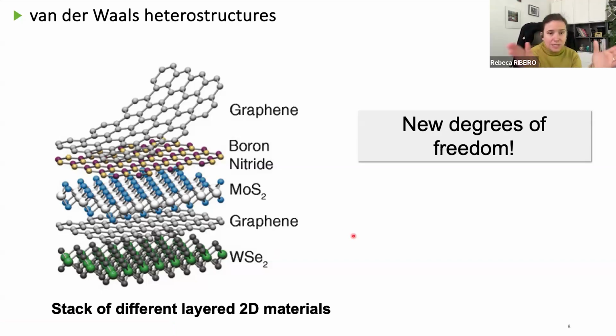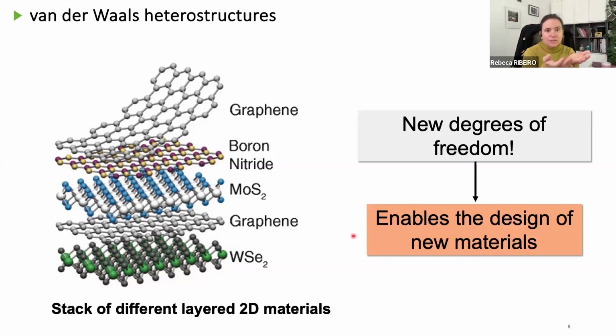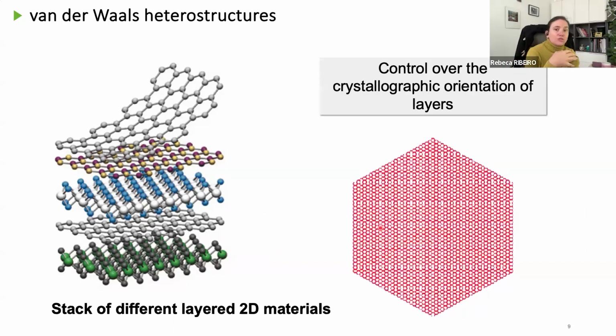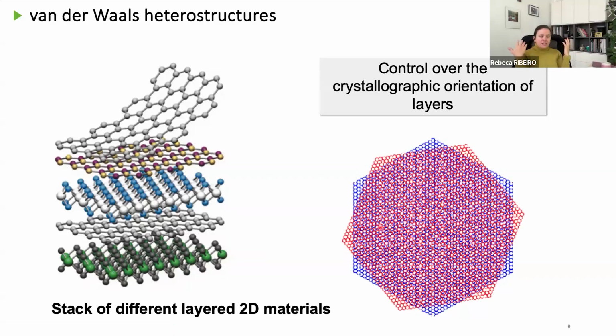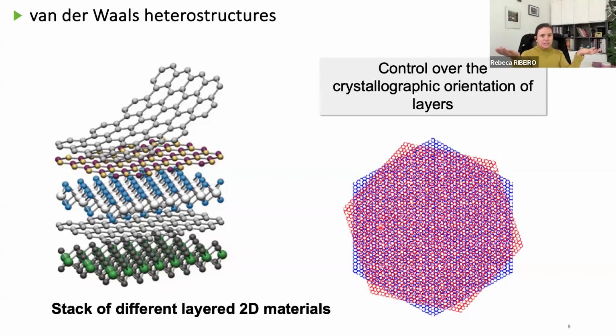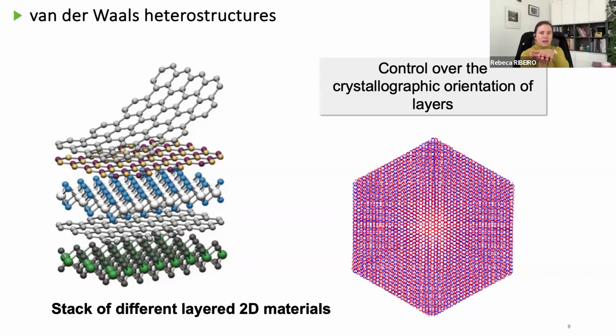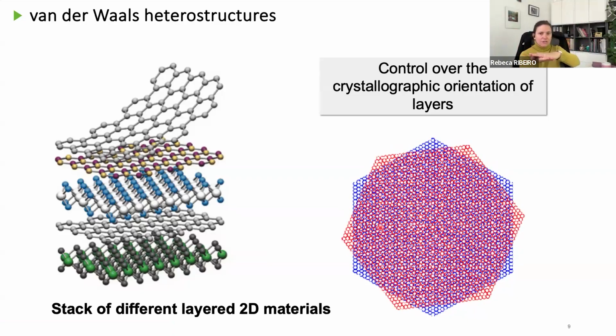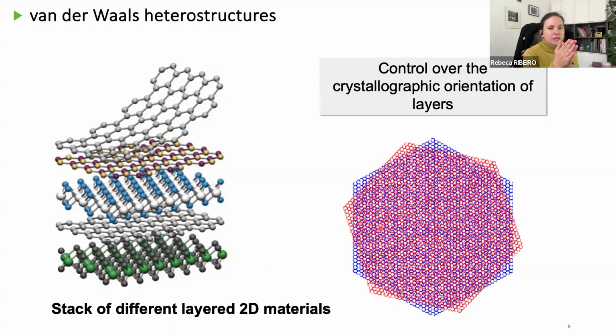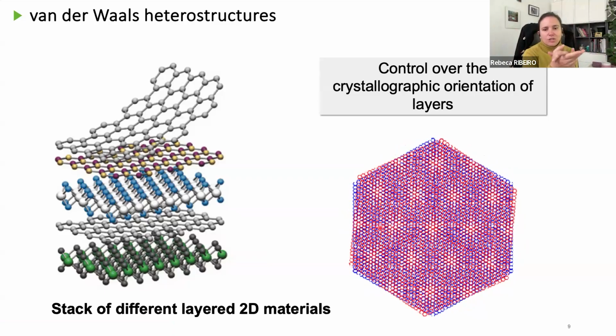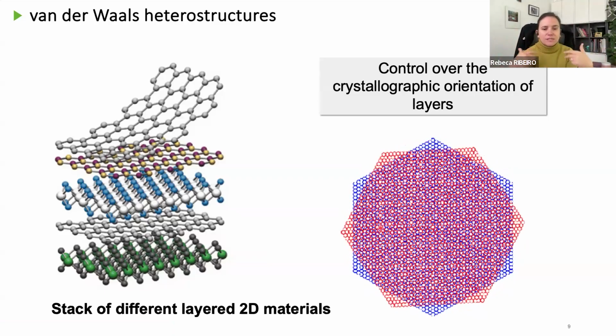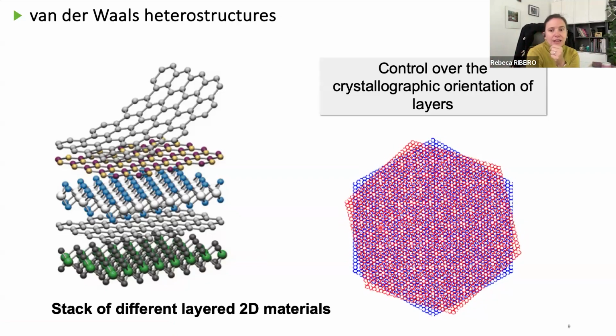So now we have different materials. We can put these materials on top of each other, but more importantly, now we can design the properties of our materials. And one of the preferred methods in my laboratory is through the control of the crystallographic orientation of the layers, because having independent layers, independent materials that can be stacked on top of each other, not just allows you to stack them, but to change this crystallographic orientation. And you might think that, okay, this modifies the electronic structure if I'm talking about two active materials, like, for example, two layers of graphene. And in fact, that's the case.